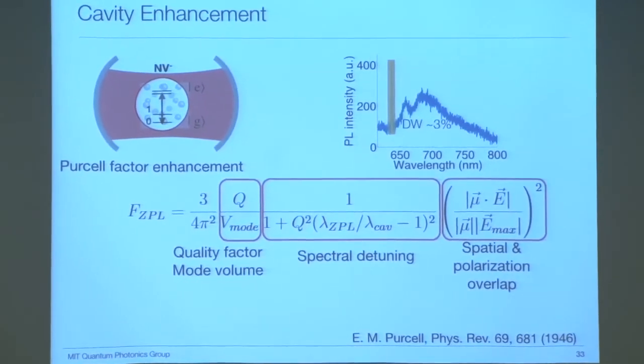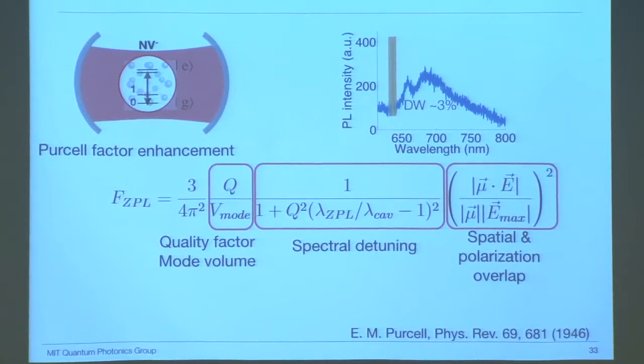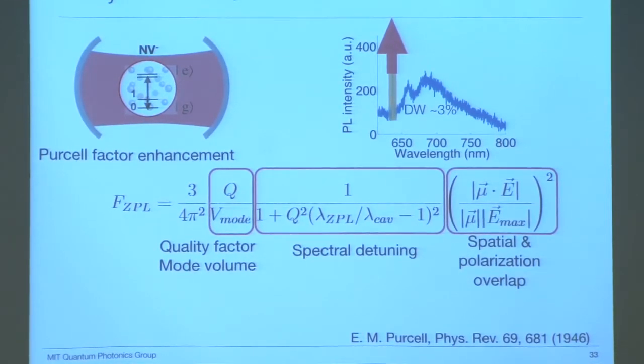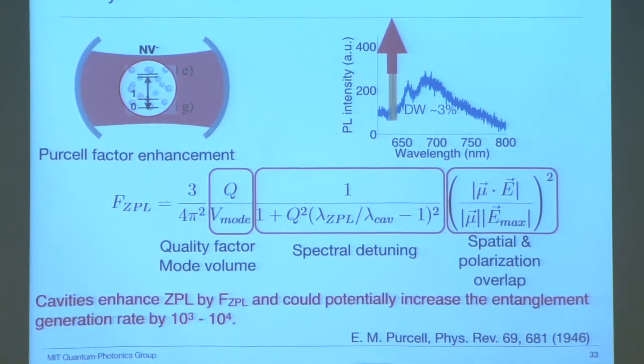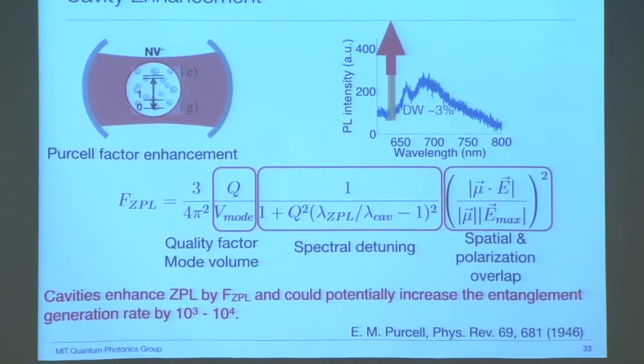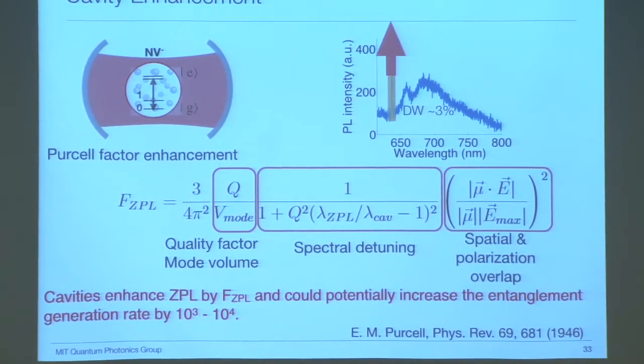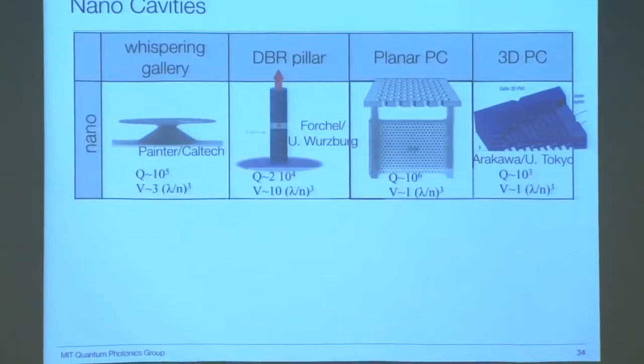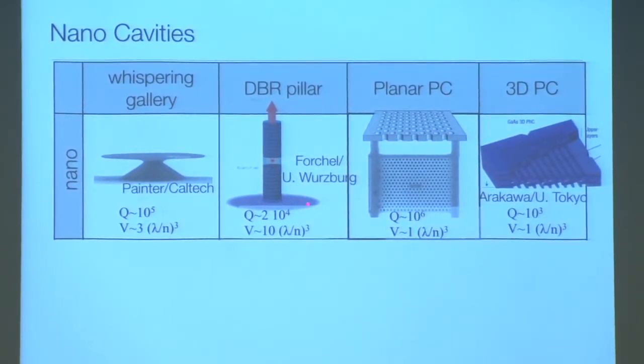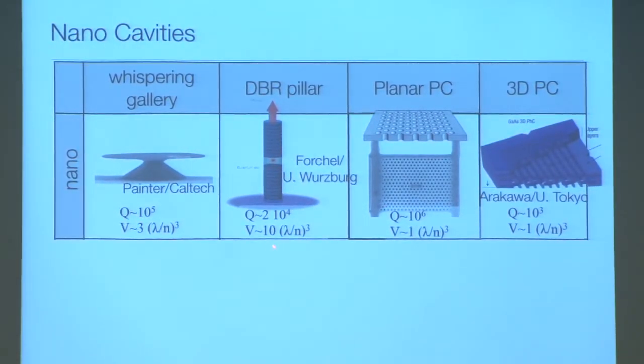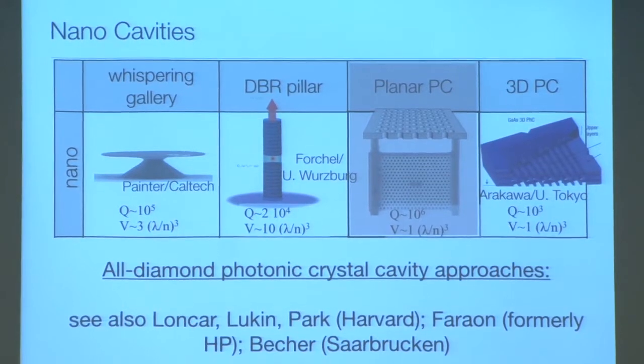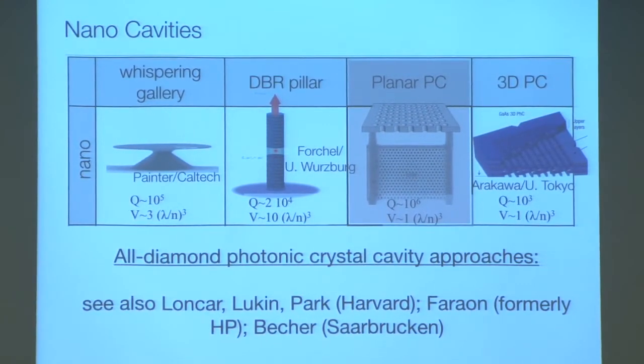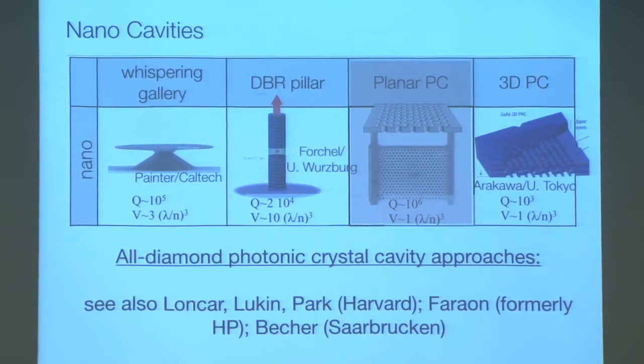In the case of an NV center, when the cavity is overlapping with the NV ZPL, emission will be greatly enhanced by tens or hundreds of times. And this means we can potentially increase the entanglement generation rate by 3 or 4 orders of magnitude. Here are some of the more commonly used nanocavities with their respective quality factor and mode volume. As you can see, the photonic crystal cavities have the largest Q over V ratio. That's also why other groups, such as Loncar, Lukin, and Park groups at Harvard, and others in Germany, are also pursuing photonic crystal cavity fabrication.